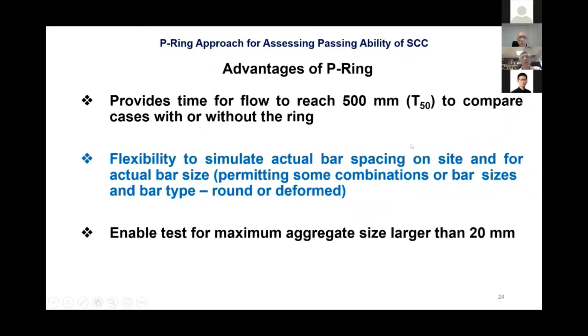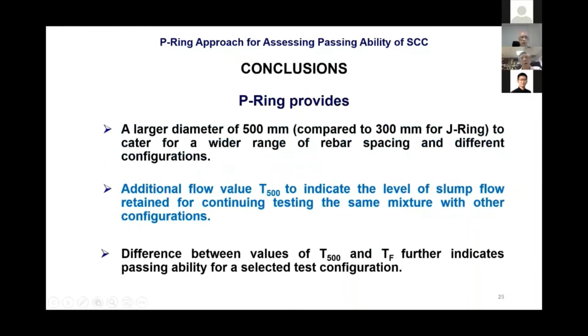Now, I have to move a bit faster so that we can get on to the next topic. Basically, the advantage of the P ring is a bigger diameter, enabling us to have more combinations of bar spacing and blockage, and also to test bigger aggregate. At the moment, if you've got 40 mm aggregate, you have difficulty doing the J-ring test. The P-ring also enables us to get the flow value of the T500 in addition to the T300, and we also have the TF, that means the final time it stopped flowing. So all these are additional values that we can get if we start doing the P-ring.